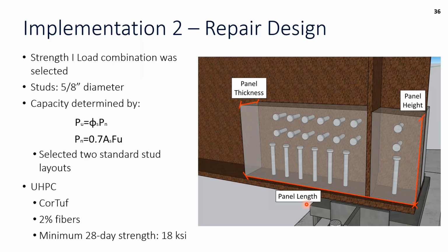So here's an overview of the repair design. Similar to the first repair, 5/8 diameter studs were used. We looked at the strength 1 load combination for capacity. Here are the stud equations that are represented in the guideline as well. And one of the nice things is that whereas the first bridge, we had a whole bunch of different parameters in terms of skew and beam height and types of beams that were used, in this project, we were able to use 2 standard stud layouts, and I'll show those more on other slides.